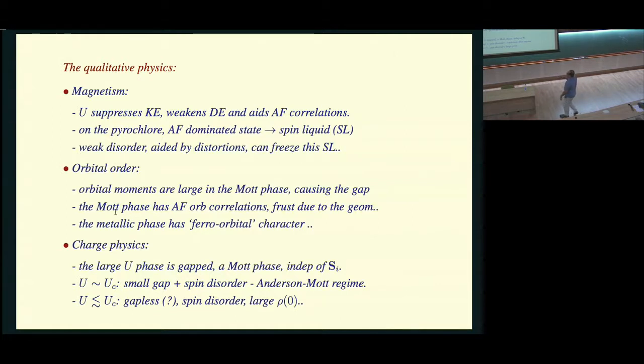The orbital order or the orbital degrees of freedom are the equivalent of spins in the parent Hubbard model, and in the deep Mott phase you will end up with an orbital liquid rather than a spin liquid. So the orbital variables are not going to be simple antiferro because they live on the pyrochlore, and you will end up with this peculiar looking short range correlated phase there.